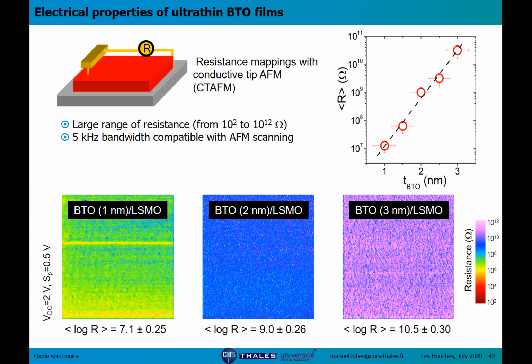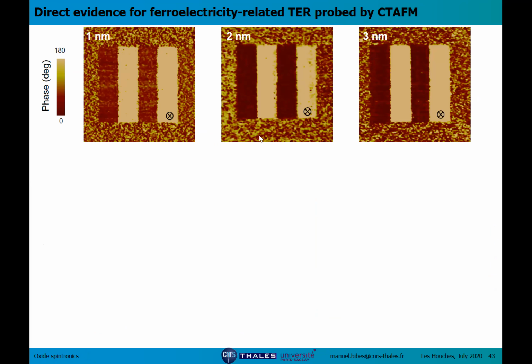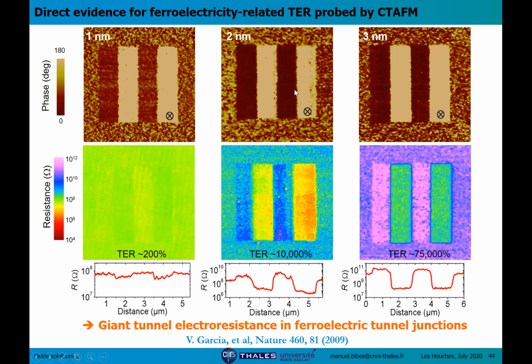So now we can directly probe how the resistance varies when we measure a region where the polarization is pointing down or pointing up. And these are the results. You can see, for instance, for 2 nanometers, we have a strong difference of resistance, depending on whether we measure a region which is poled up or down. And the variation here is about 2 orders of magnitude, corresponding to about 10,000% of tunnel electroresistance, and it's even higher for 3 nanometers. So we have tunnel electroresistance, but it's even giant in these devices.